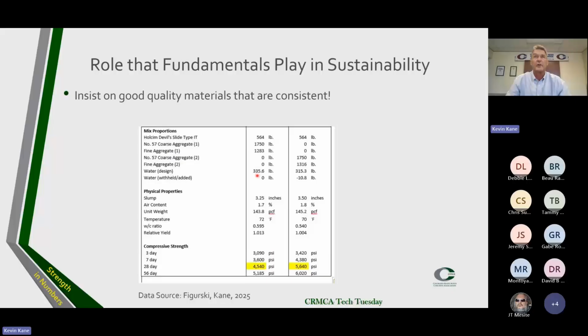This mix took 335.6 pounds per cubic yard to get that 3 1/4 inch slump. This mix, with properly graded and proper clean aggregate that met the specification, only took 315.3. And we actually had 10.8 pounds of water left over. It produced the same amount of workability. Look at the difference it made at 28 days in the compressive strength, over 1,000 PSI.